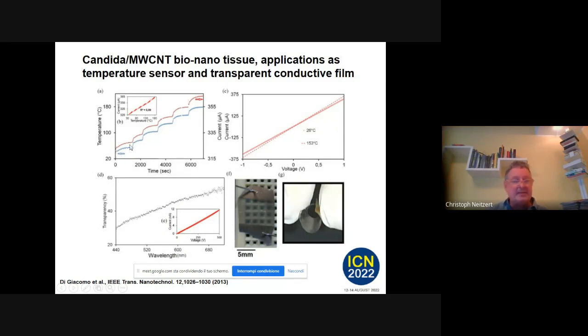If you see, this is temperature and this is the conductivity, and you see it's linear. We found it's not very conductive. It's a microampere, 1000 times less than a milliampere for 1 volt. But it's conductive, and you see change in the electrical characteristics.